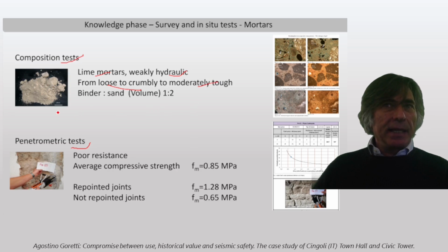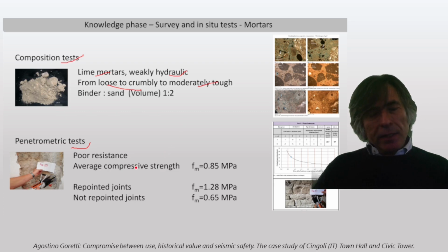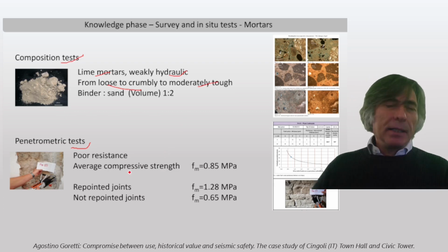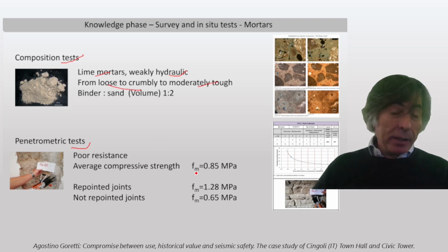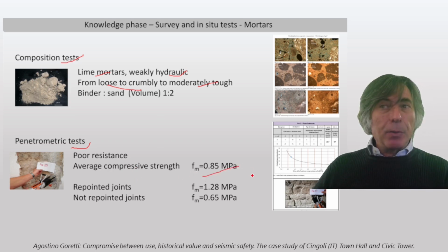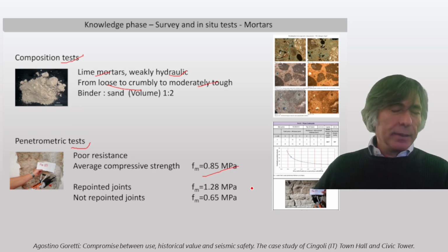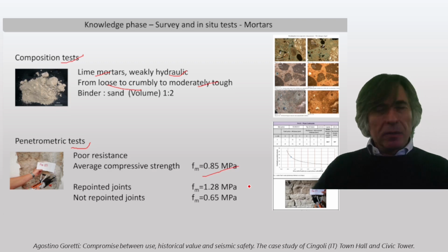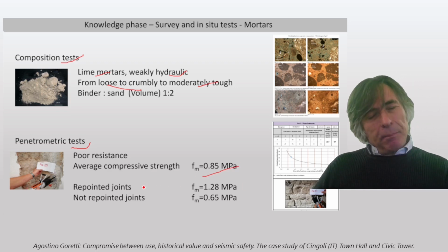So basically, it has some friction behavior rather than cohesive behavior. And this is also demonstrated by the resistance. The average compressive test strength from the penetrometric test is 0.85 megapascal, which is not so high. But then I decided to perform some additional analysis.